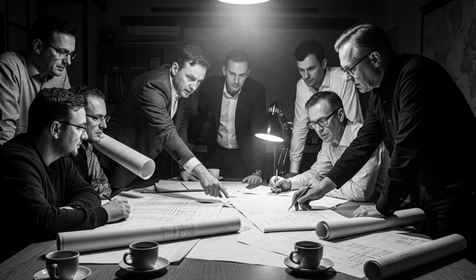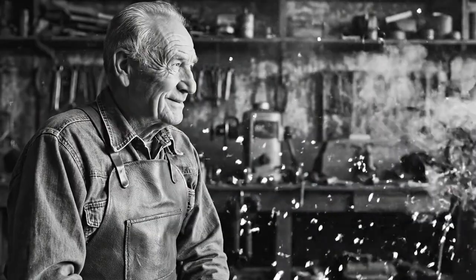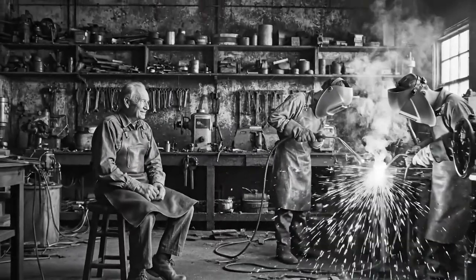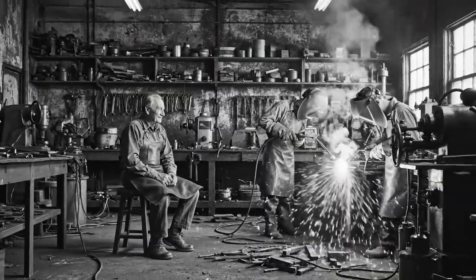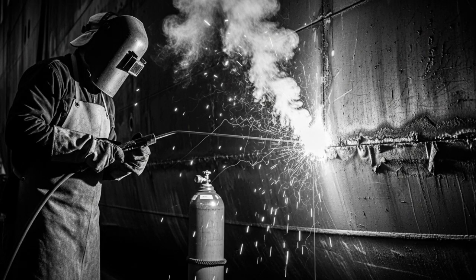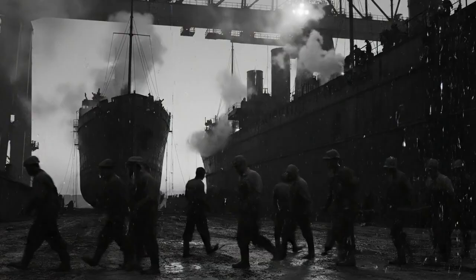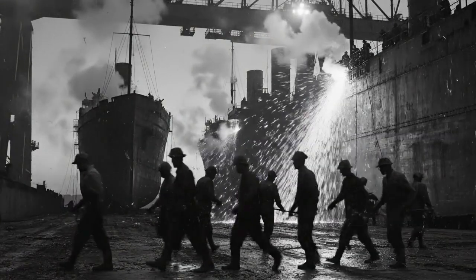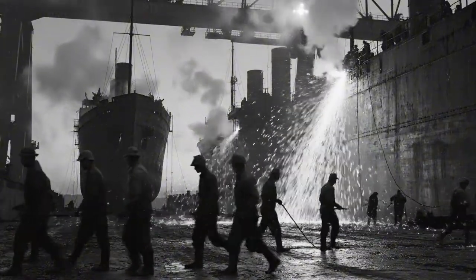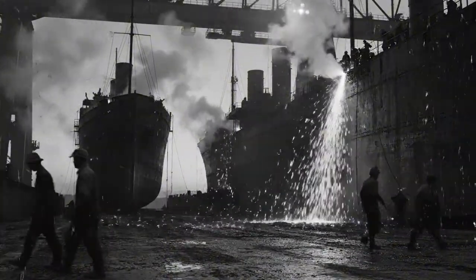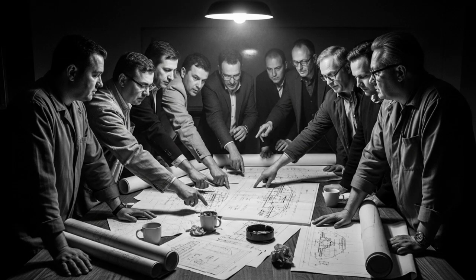But it is not a weld failure. It is a failure of the steel plate itself. The metal tears apart adjacent to a weld. The weld itself remains intact. Foster repeats the test with 5 additional sections. Same result. The welds fail at pressures 35 to 42% higher than riveted joints. The welds are stronger. The Navy receives the report on May 7th. The response is immediate. All future Liberty ships will use welded construction. The pilot program is authorized to expand from 10 ships to 50 ships.